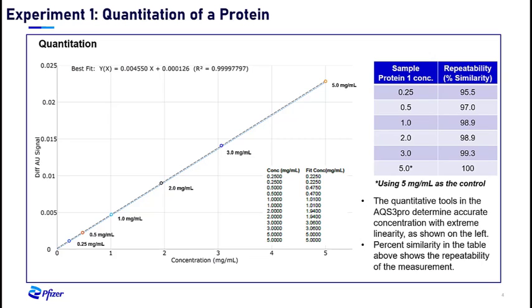On this next slide, you'll see the linear regression graph showing extreme linearity with the sample set. Here we've set our 5 mg per ml as the control. As you can see, the fit is very good with the R2 of 0.9999. In the table to the right in blue, you'll see the repeatability of the samples is recorded. And again, we've set the 5 mg per ml as our 100%. You'll notice the numbers are quite good until you get down to the 0.25 mg per ml sample where the repeatability drops, but only down to 95%.